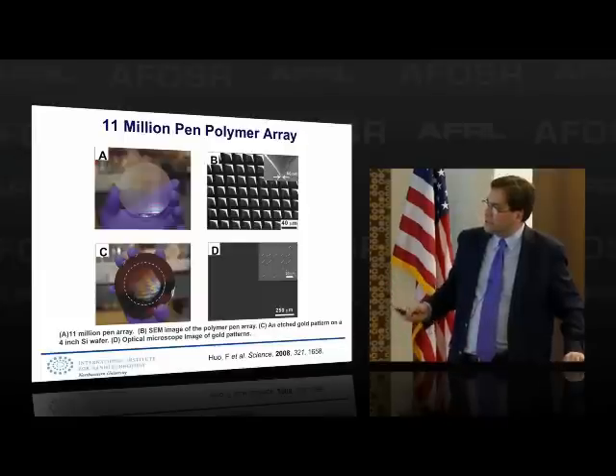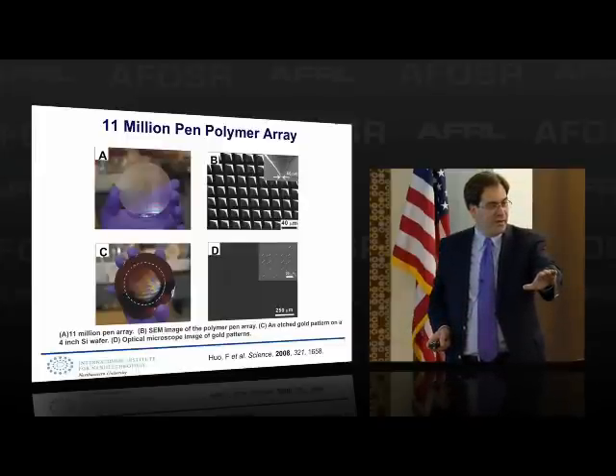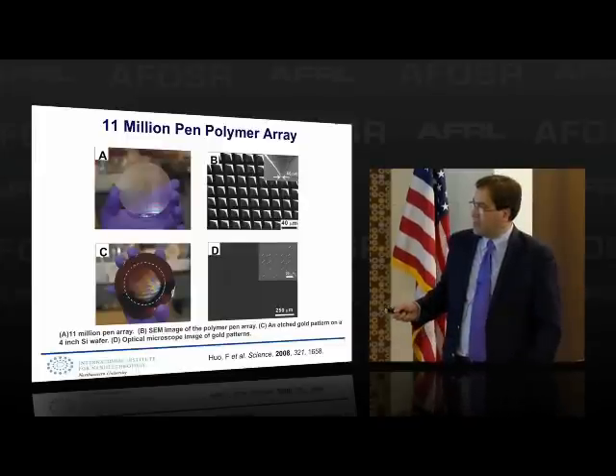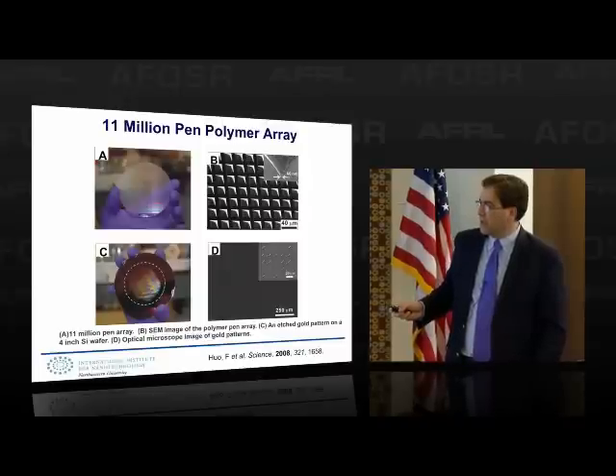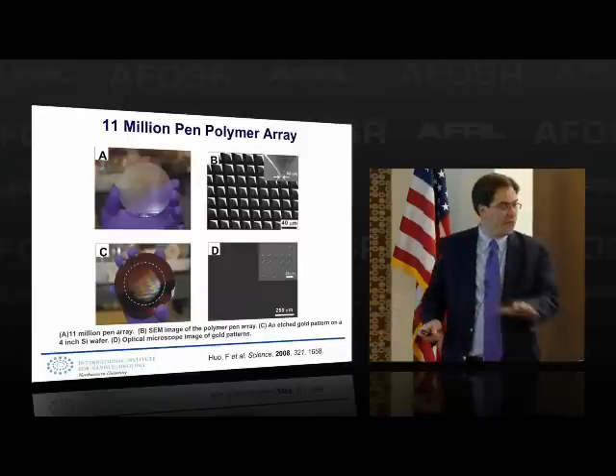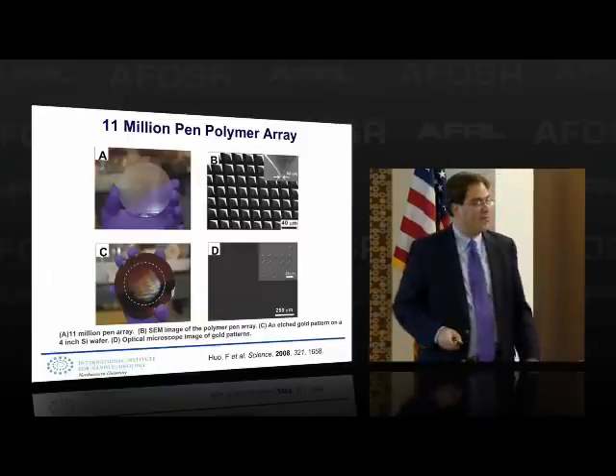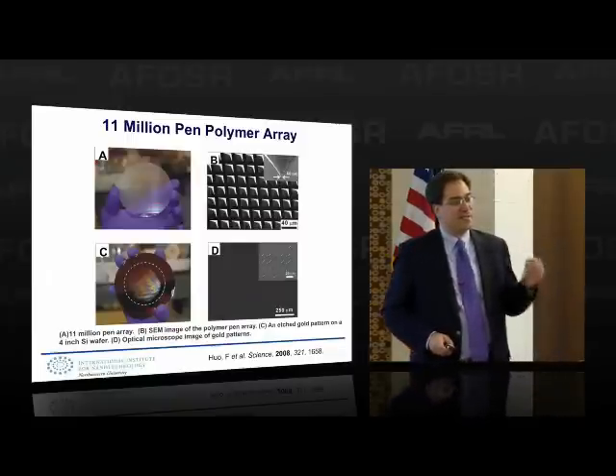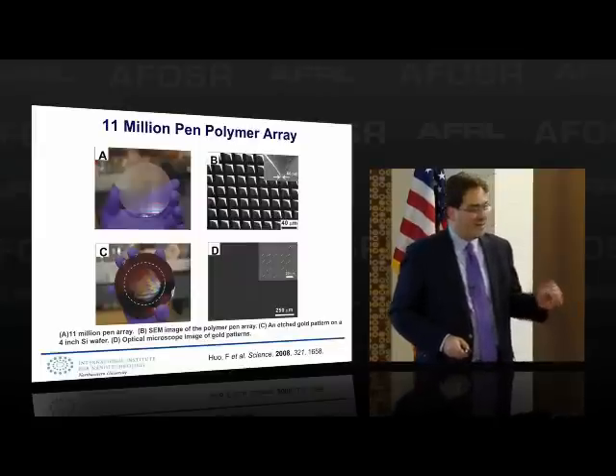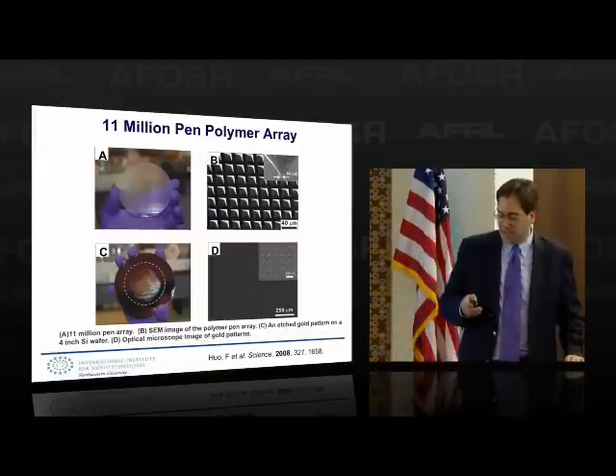And in fact, this was the first experiment we did with the 11 million pen array. We put it into the device, bring it down, depositing alkanethiol on gold. It's octadecanethiol, I believe, in this case. And then we move it over, make another dot, move it over, make another dot, move it over, make another dot. And you can see the 4 dots duplicated 11 million times. Each dot takes less than a second to make. And we'll talk about resolution in a second.